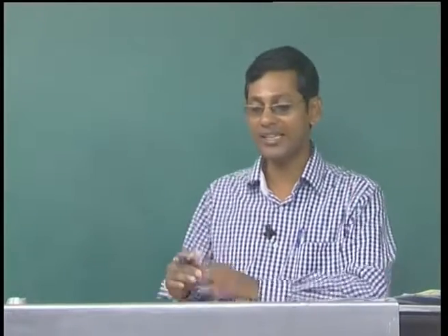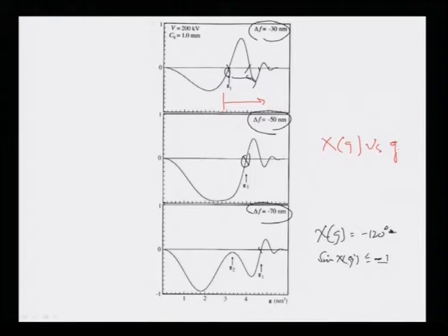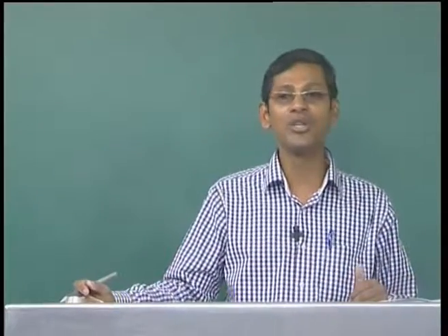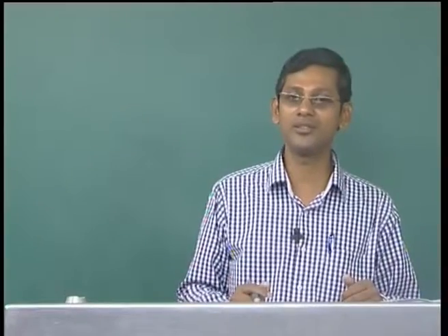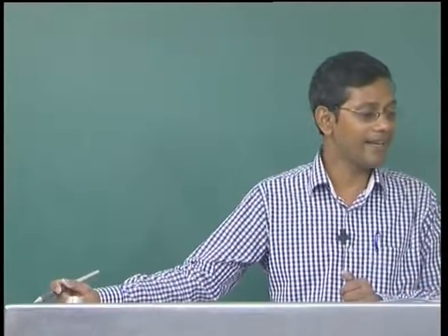That is the question we need to ask ourselves, because if we can extend this to higher g numbers, and g is the spatial frequency, we may be able to achieve much better information in real space, because g is in reciprocal space. A higher value of g means a lower value of x, y or z, the real space variables. So, if we can extend g to higher values and include them in the transfer function of an electron microscope, we will be able to achieve much higher resolution and much higher information limits. So, is that possible?